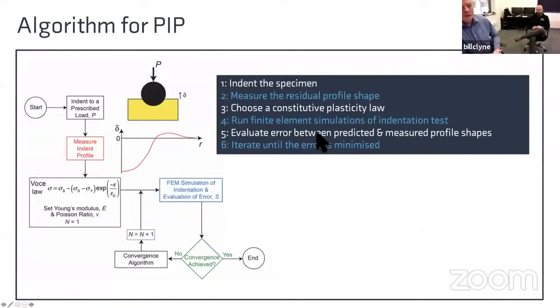So here's the basic idea pictorially. You start by making an indent to a prescribed load using a spherical indenter, a relatively large spherical indenter. You measure the profile rather carefully, and then you need some kind of constitutive law to describe the plasticity. We use the Voce equation. There are alternatives, but you need to be able to simulate the plasticity.